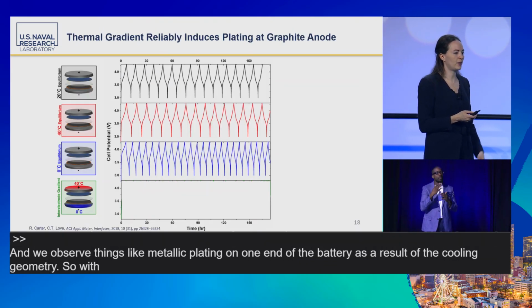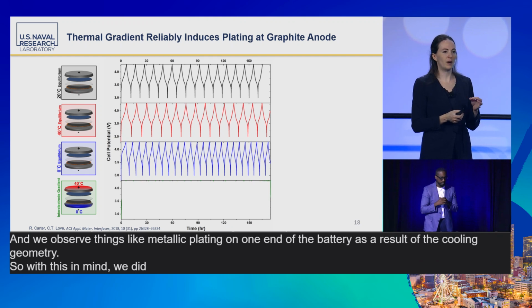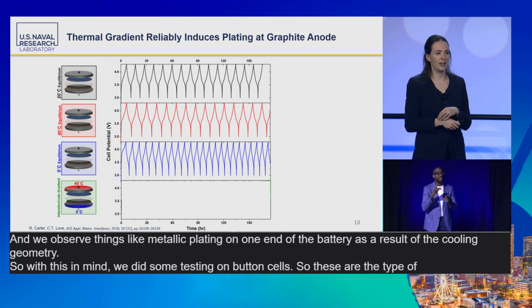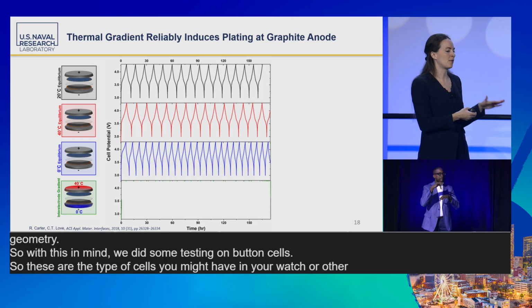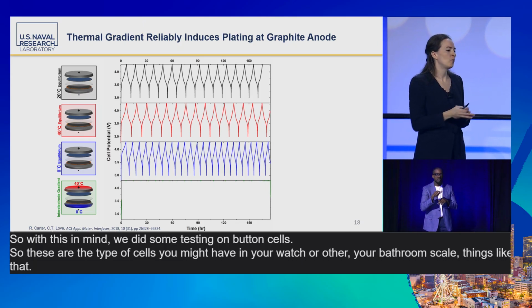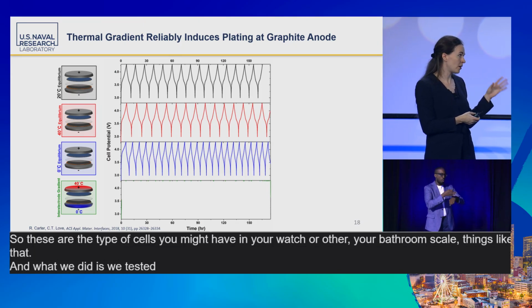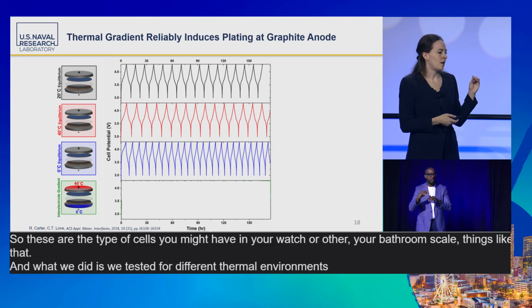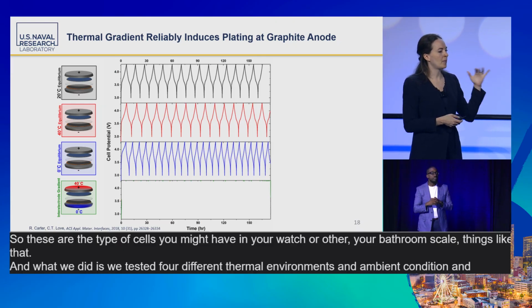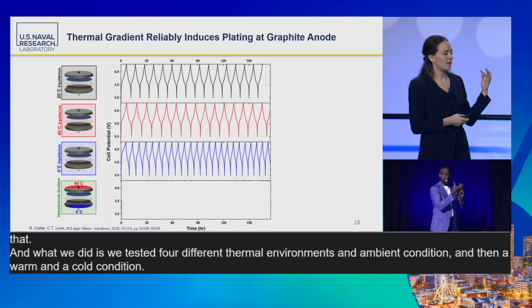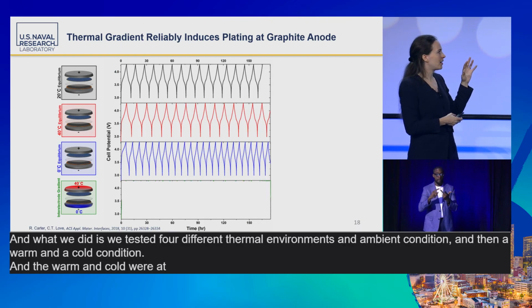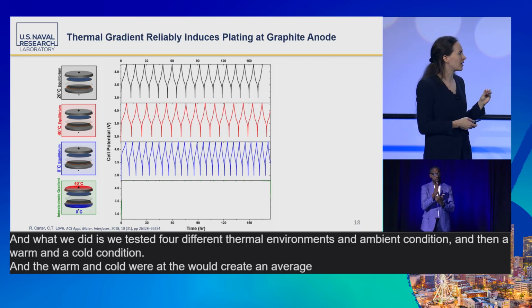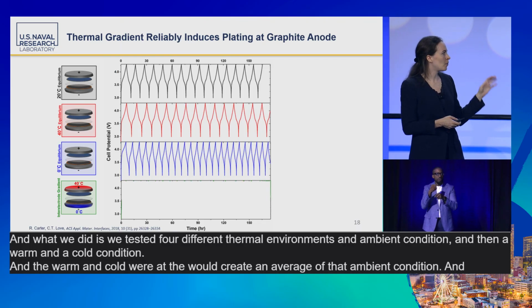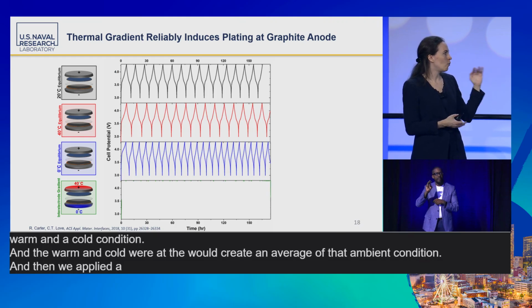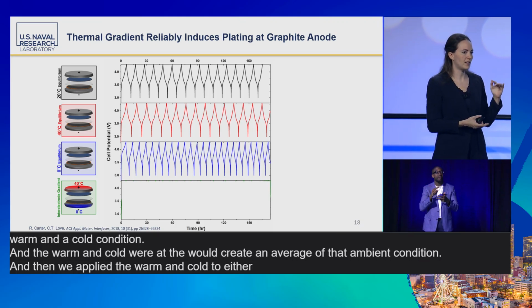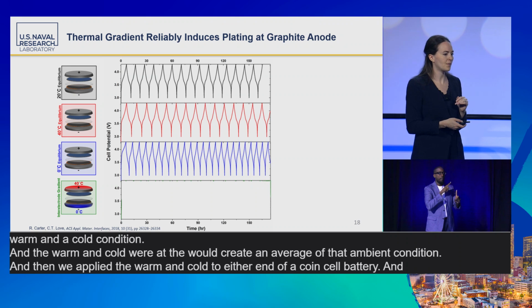So with this in mind, we did some testing on button cells. So these are the type of cells you might have in your watch or your bathroom scale, things like that. And what we did is we tested 4 different thermal environments, an ambient condition, and then a warm and a cold condition. And the warm and cold would create an average of that ambient condition. And then we applied the warm and cold to either end of a coin cell battery and produced the cycling.